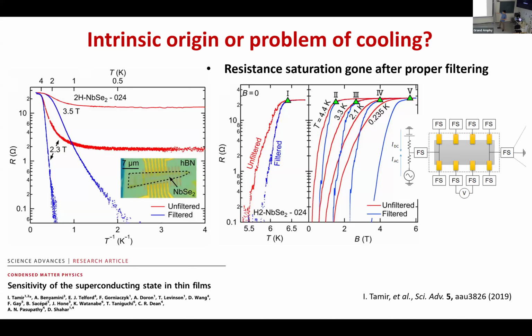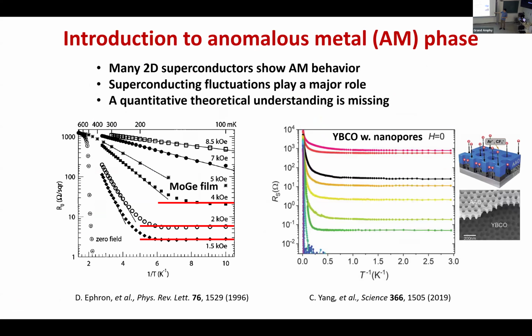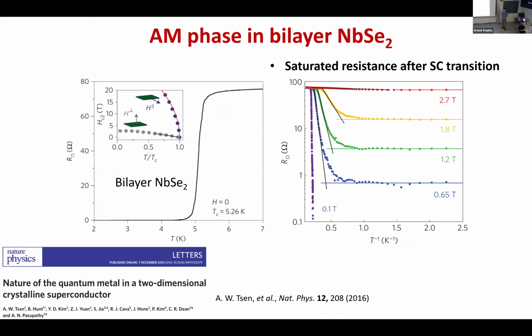Yes. Sorry for the non-experts. What is filtering? You add some low-pass filters. For example, some RC filters, and for dilution fridges you can have these thermal coax cables, so that can filter out all the high-frequency radio frequency signals. But still, some groups observe the saturation even after filtering. Exactly. So I will also mention that part. The thing is, for niobium diselenide, after this paper, people became very careful about filtering. And for example, this YBCO paper, this is at very high temperature, they also carried out the measurement with filtering, and they still see this. So somehow, radio frequency noise cannot explain everything.